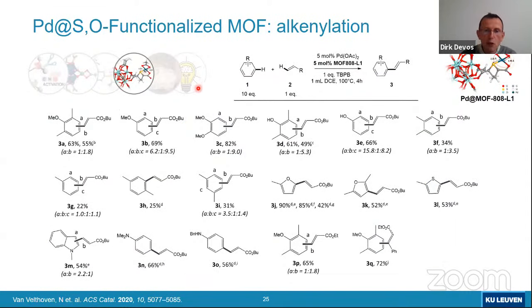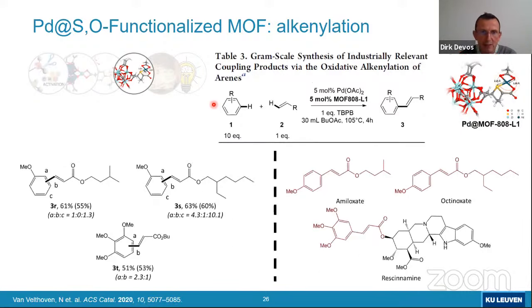We did a whole substrate scope with this system. So actually you can use it in a very flexible way for doing all these alkenylations. And then you will see that with these methoxy substituted arenes, but also with, for instance, the furans and so on, we got to high yields in many cases. The selectivity is one, of course, that could be improved because here we are in a system, this MOF 808, that has very large pores. So there is not really a way yet that by the porosity you could influence the positional selectivity of the alkenylation in this case.